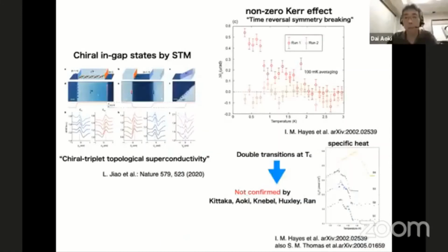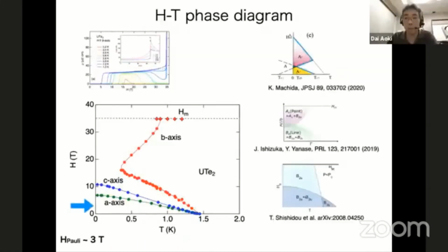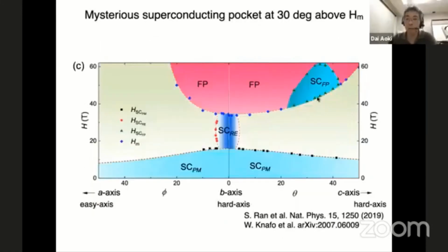And what is interesting is that reentrant superconductivity appears here. So you see here, this is a metamagnetic transition, and this region is the spin polarized phase. In the spin polarized phase, superconductivity reappears. So there is some similarity to ferromagnetic superconductivity, but well, we don't know yet. But this is also an interesting point, I guess.